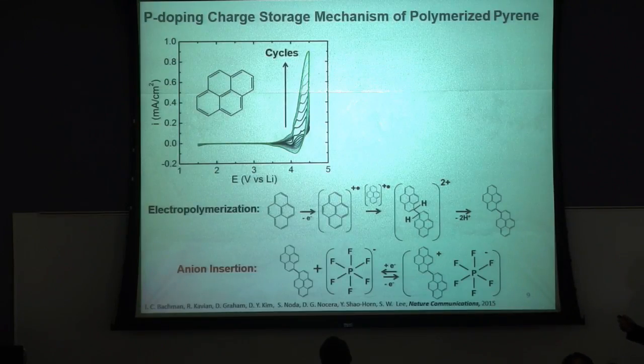Then we can see, during the cycling process, a gradual increase of the charging and discharging current, a gradual increase of this kind of oxidation and reduction peak. This is related to the electrochemical polymerization process.